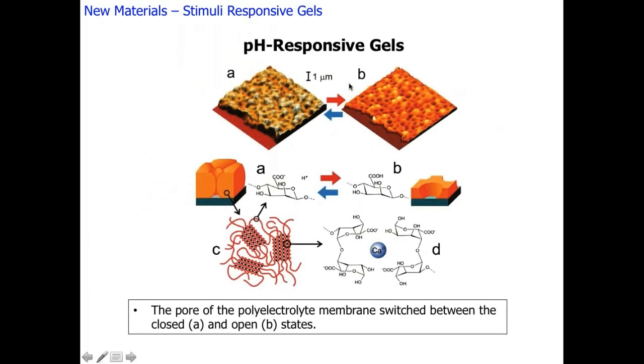Here, we have a pH-responsive gel. As I mentioned earlier, the presence of divalent salts with polysaccharides tends to increase its viscosity, and as in this case, the polyelectrolyte membrane switches between a closed and an open state. And here is an example of an effective use of AFM to look at the change in morphology with pH response. So the corresponding change in viscosity can also be tracked by a change in the morphology as observed by AFM.